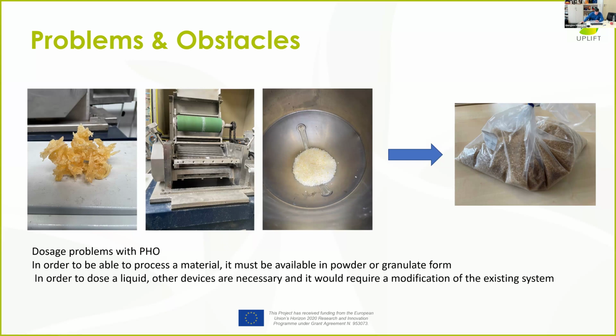AIM+, as a partner also in this Work Package 6, took this material and found a very good solution to compound it and mill it. They cool it down with liquid nitrogen, and they mix it, they granulate it, and so we get this granulate from our partners. This shows also the difference that some partners are very well equipped, and the industrial partners don't have the opportunity, for example, to cool it down with nitrogen. It is too expensive, but we found a very good solution for a problem that we were not able to solve. At the end, we got this granulate from AIM+, and we were able to compound it also in our formula.